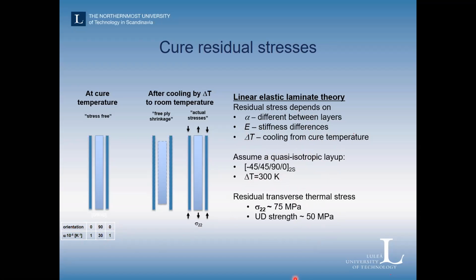And if we just calculate a simple estimate, we notice that in principle, the stresses that are generated in our cure are up towards 75 megapascal, which is almost in the range of the theoretical strength of a 90-degree layer in the transverse direction. So it is more surprising that it doesn't crack more.